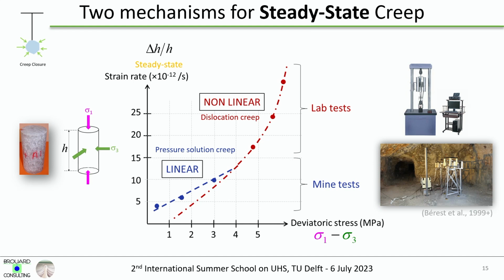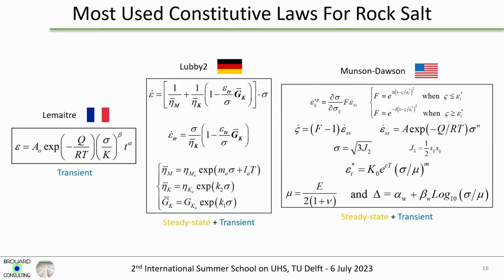And it was observed that this prognosis was correct. When we consider a small deviatoric stress, we have a linear relationship between the strain rate and the deviatoric stress. And so we have two mechanisms that are called dislocation creep for the nonlinear process and the pressure solution creep for the low deviatoric stresses.